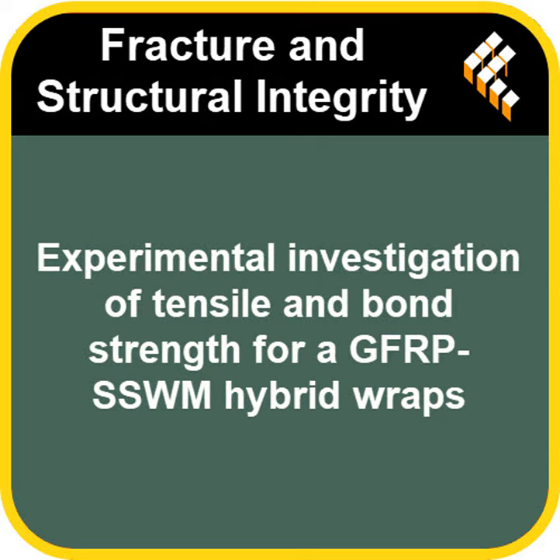Okay, but here's something fascinating. This capacity utilization ratio. Can you explain that? It sounds important. It's incredibly insightful. It basically asks, okay, we know how strong the material could be based on tensile tests, but in a real bond situation, how much of that inherent strength are we actually using before something else fails, like the bond itself or the concrete? Right. What's the real-world efficiency? Exactly. And for the pure GFRP wraps, the utilization was surprisingly low, only about 40%.